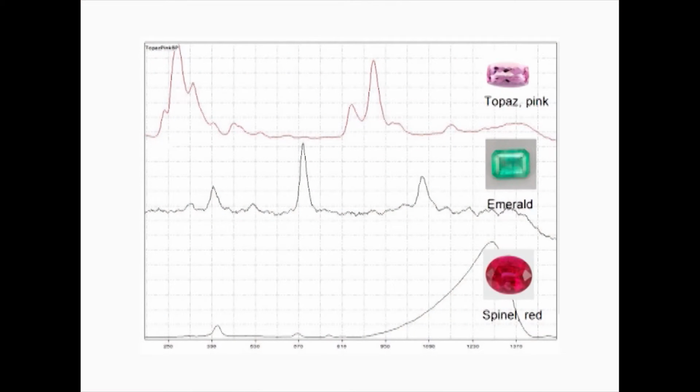The causes of luminescence are varied but are mostly due to impurities, which are also called activators, or due to defects in the crystal lattice. In general, the presence of iron inside the gemstone kills or suppresses luminescence. Luminescence effects are useful in gemstone identification, especially for differentiating between certain natural and synthetic gems.